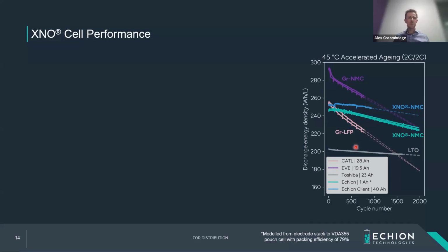LTO lasts for a very long time, but does have this limitation on energy density that you can actually hit. And what we show for the niobium chemistry here is two results. One result from our labs in Cambridge, where we work in small pouch cell prototypes modeled out here. And then a result from one of our clients working in 40 amp hour cells, showing that we can achieve that similar energy density that you can have for a graphite LFP chemistry.